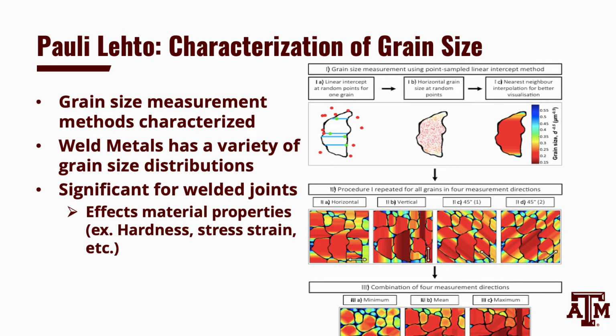Weld metals have a variety of grain size distributions that can influence different material properties. Lehto et al. state that grain size measurement for homogeneous equiaxed microstructures will not work for columnar grains due to directionality. This is identical to what I found when trying to use ASTM E112 on additive materials.